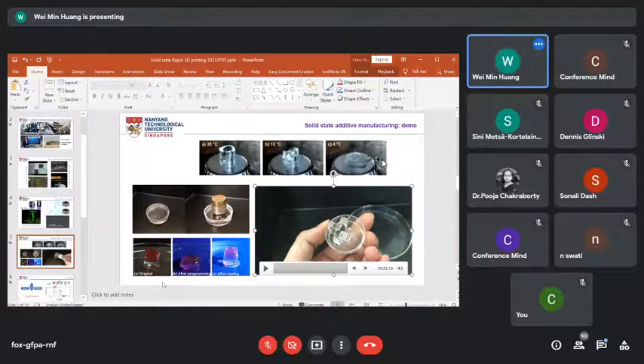The shape memory effect. This is the original shape, and we can cool it and compress it. So this is after programming, back to room temperature. It can maintain this shape. But if we cool it again, it will fully recover its original shape. So we successfully demonstrate this is a kind of rapid additive manufacturing method, and we can cross-link in the solid state, and it has very good shape memory effect, so it's able to recover its designed shape.